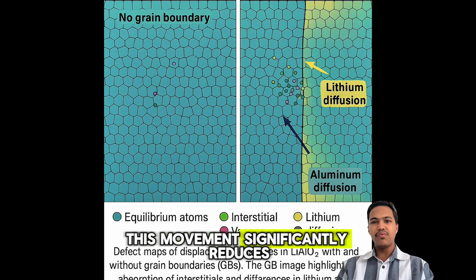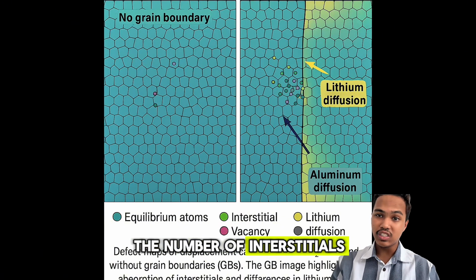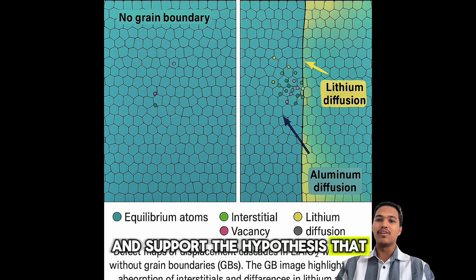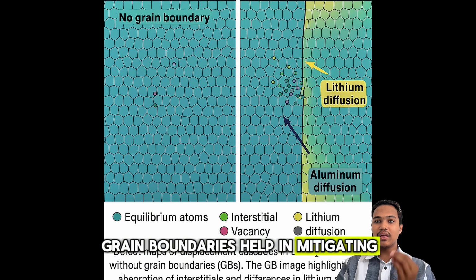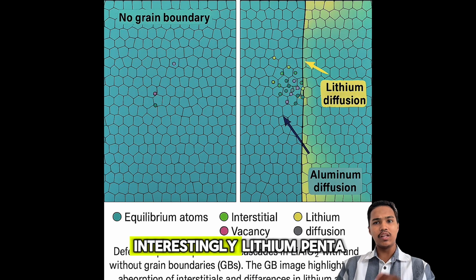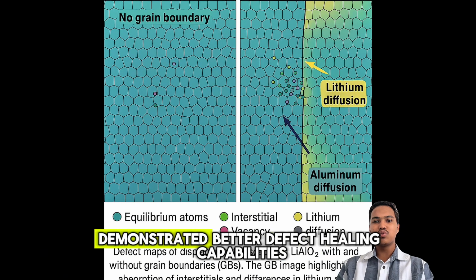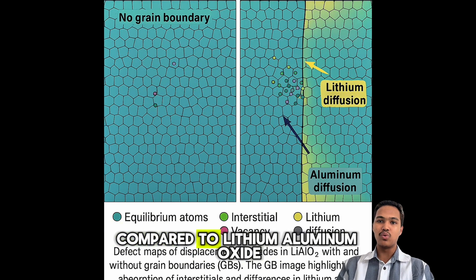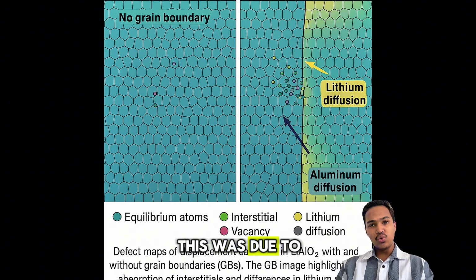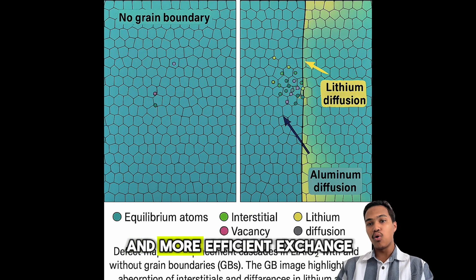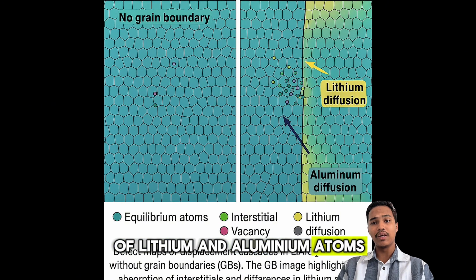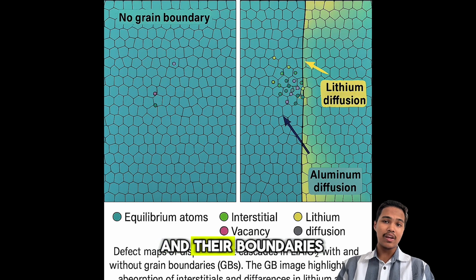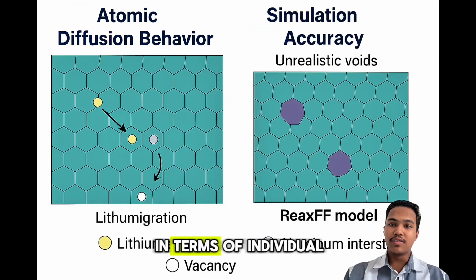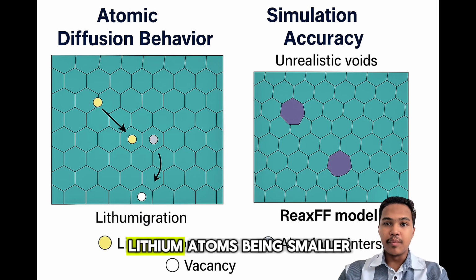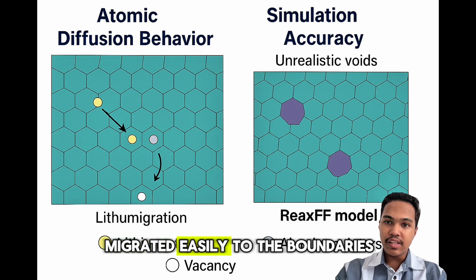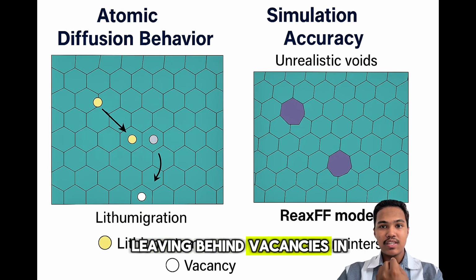This movement significantly reduces the number of interstitials in the grains and supports the hypothesis that grain boundaries help in mitigating radiation damage. Interestingly, lithium pentaaluminum octaoxide demonstrated better defect healing capabilities compared to lithium aluminum oxide. This was due to higher atomic mobility and more efficient exchange of lithium and aluminum atoms between the grain interiors and their boundaries. In terms of individual atomic behavior, lithium atoms, being smaller and more mobile, migrated easily to the boundaries, leaving behind vacancies in the grains.